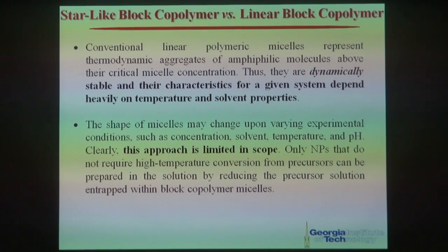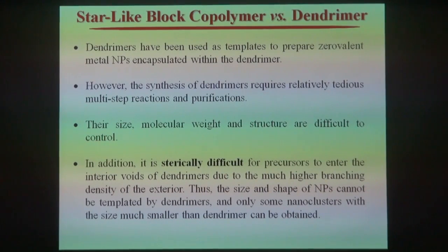Only nanoparticles that do not require high temperature conversion from precursors can be prepared in solution by reducing the precursors and entrapping them within the block polymer micelles. On the other hand, dendrimers, we know, have been used as a template to make zero-valent metal nanoparticles. However, preparing dendrimers requires relatively tedious multi-step reactions and purification. And the size, molecular weight, and structure of dendrimers are very difficult to control. Moreover, it is sterically difficult for precursors to enter the interior voids of a dendrimer because of the highly branched exterior on its surface. So the diffusivity of precursors into the interior of a dendrimer is quite difficult. Thereby, oftentimes what you get is just nanocrystals instead of fully templated nanoparticles from the dendrimer.